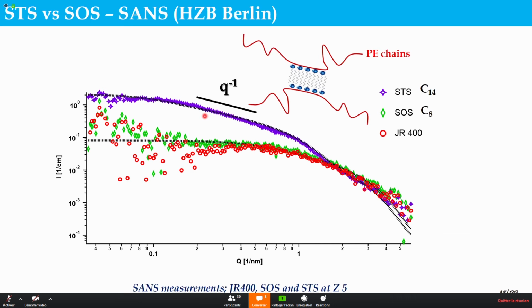Okay, I think I agree completely. The fact that you have a considerable contrast between the spherically shaped scatterers and those which are roughly cylindrically shaped, always with the distribution imperfections, etc., is a very good indication that you have something different, and that the Q^-1 region of your plot corresponds to a cylindrical shape.